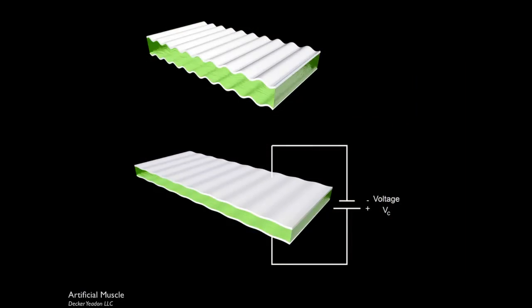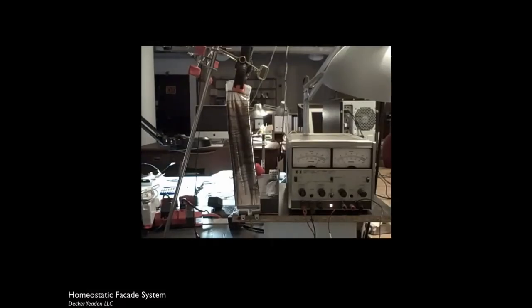Since we're not quite that far yet and we wanted to work with that muscle a little bit more, we started using a product from Danfoss that uses silver electrodes on both sides of the polymer, which are applied in a corrugated manner. So as soon as the polymer stretches because the electrodes are attracted to each other, they will just even out. But that really limits the movement of your actuator. This is really a very small increment.